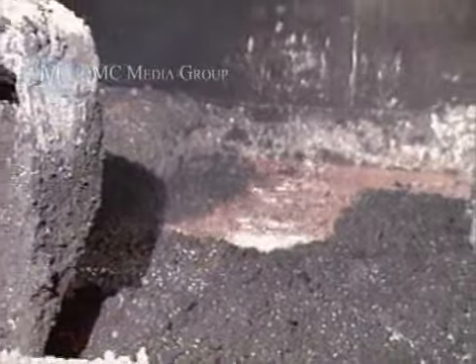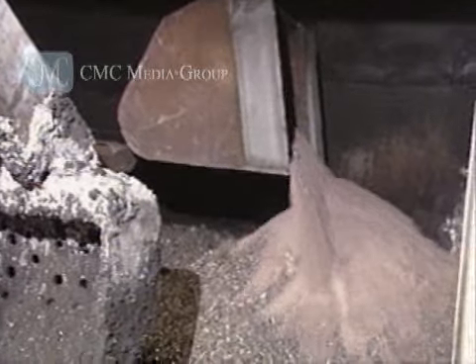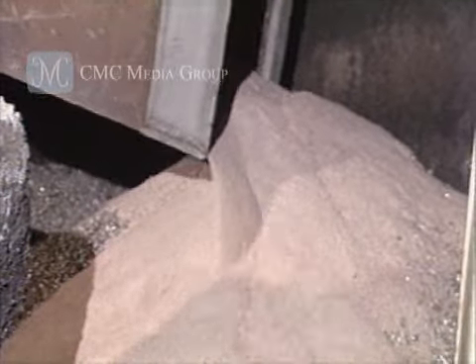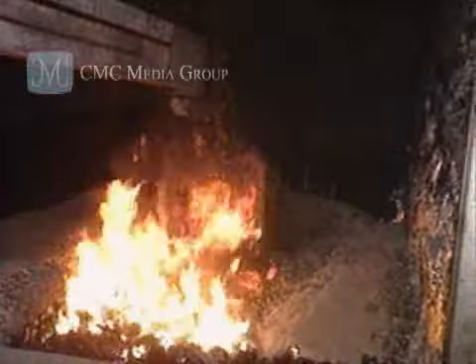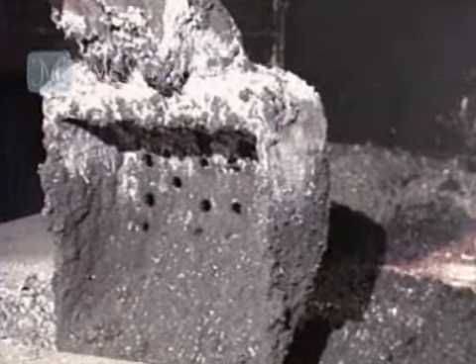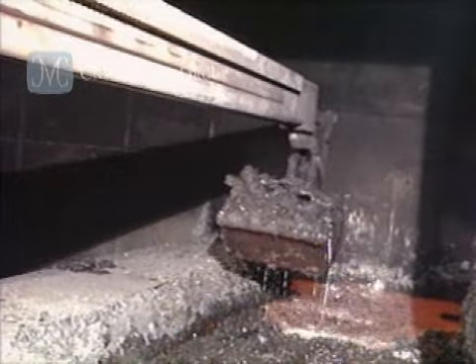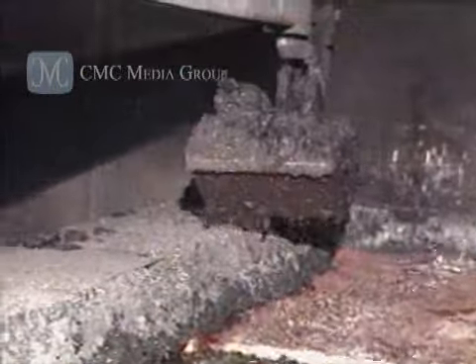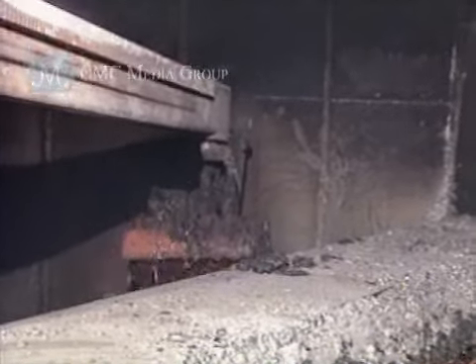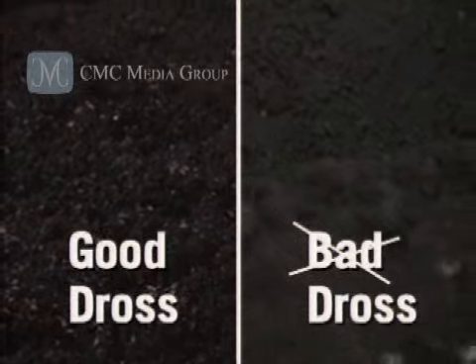Notice the metal temperature, the charge being added, flux being added, scrap being worked in immediately, the bucket is being preheated and has open holes. See how quickly the aluminum drains because separation has already taken place. The lack of burning and smoke. Finally, the difference in dross. One was burning, one was little beads of dross.